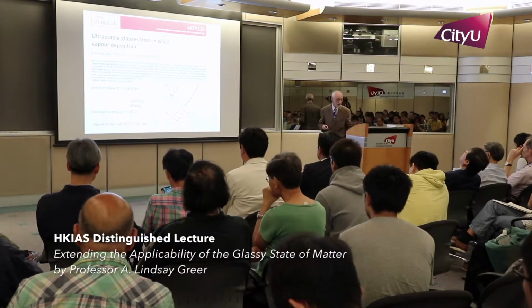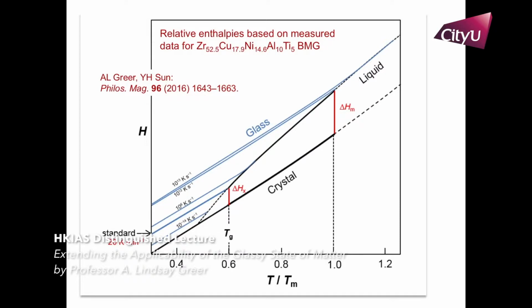So these are quite interesting states. We can actually quantify this. I showed you many times this picture of a liquid forming a glass. These are based on actual data, so it doesn't look quite the same shape as I showed already. Cooling the liquid at 20 Kelvin per minute, which is a standard sort of rate, would pull you off on this line in terms of enthalpy of the system.